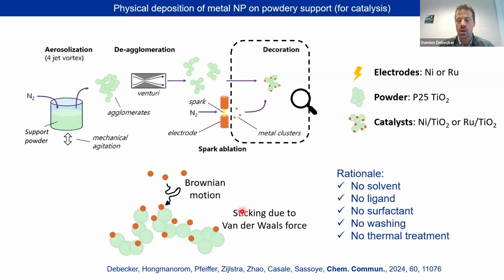What I want to insist on here is that we prepare a metal supported catalyst using no solvent. There's no solvent, organic solvent, water, whatever. There's no precursor like a salt or alkoxide or chloride or whatever. It's the pure nickel electrode. No ligand to wash, no surfactant to burn. There's no need for washing, and you don't even need to calcine or reduce it because you directly have metal nanoparticles. We will see in a second.